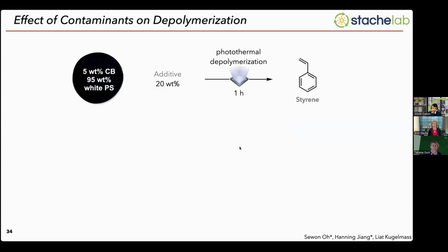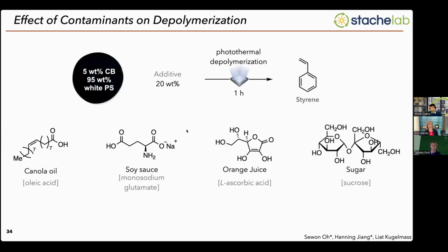We tried this out in some commercial polymers just by mixing carbon black with white polystyrene, so just melt processing these together. And what we wanted to do in this case was see what would be the effect of different contaminants on the depolymerization. We hypothesized that because this is just a purely thermal process and we're not doing any other special catalysis, impurities wouldn't really affect the depolymerization. And so we looked at different food contaminants, canola oil, soy sauce, orange juice, and sugar or sucrose. We mixed these in at 20 weight% with the polymer mixture. So it's a pretty high contaminant loading.